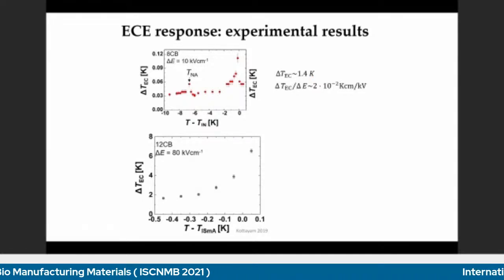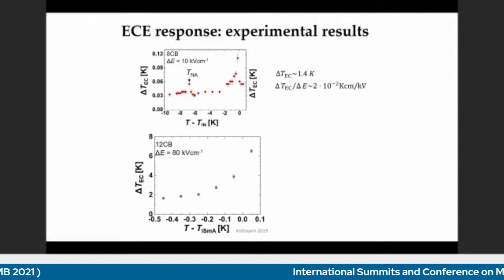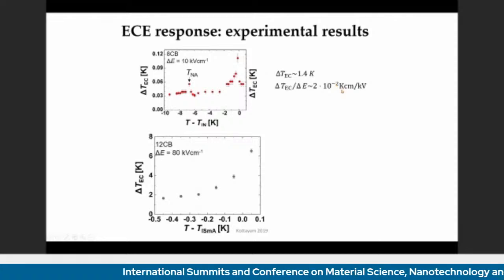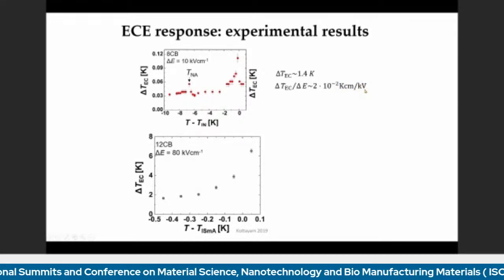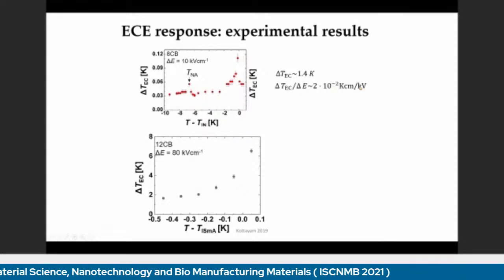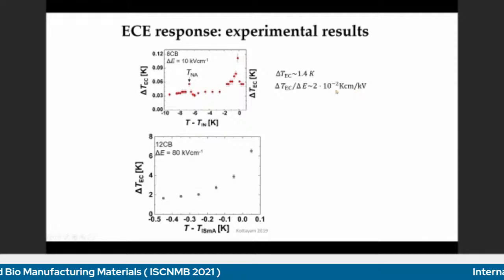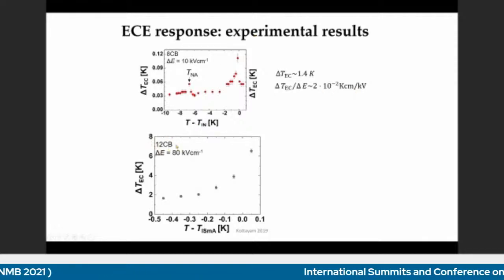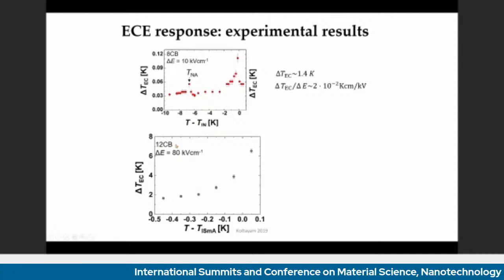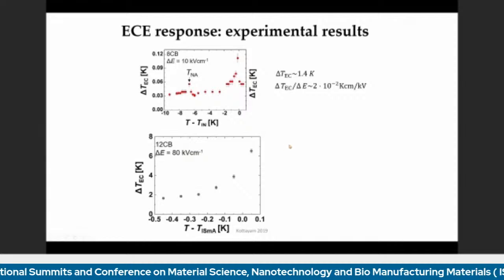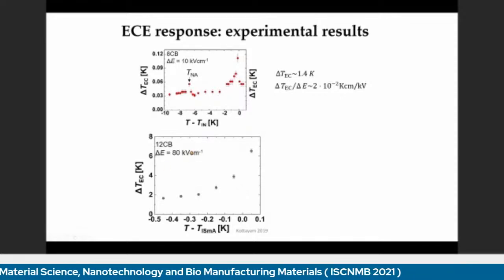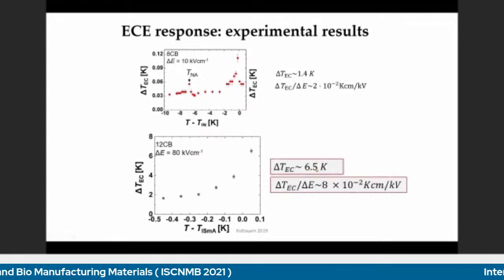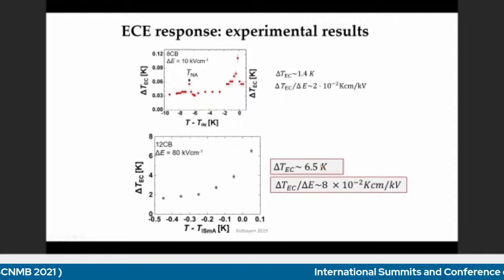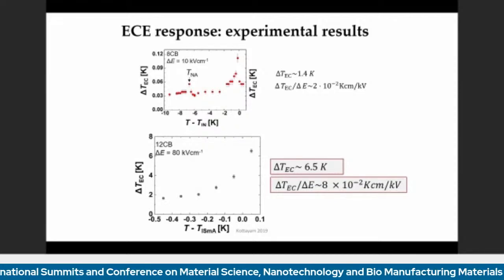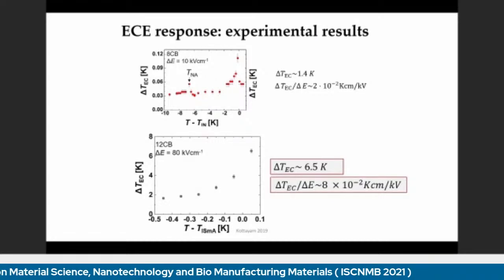And the optimal ratio between the change of the temperature and the change of electrical field is 2 times 10 to the minus 2 Kelvin centimeters per kilovolt. This is a very good result, and such materials are very good for practical application. But when the experiment was made with the 12CB liquid crystals, we see this below. We see the direct transition between isotropic and smectic A phase, and the diagram shows that the response is almost 6.5 Kelvin, which is the largest increase in the temperature induced by adiabatic changes in the electric field achieved experimentally. And this response is at room temperature.